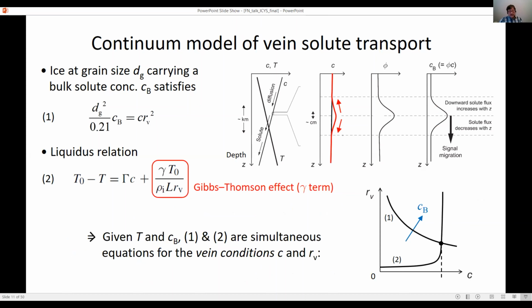Now, they actually realized in their theory an extra melting point depression coming from this term because of the curvature of the ice-water interface. And so this vein radius RV is involved. This is the Gibbs-Thomson effect. And gamma here is an interfacial energy, a non-constant. But they didn't actually include this in their calculations. And when I did, I found that the signal behavior is different, and the implications for how we interpret observations become radically different.